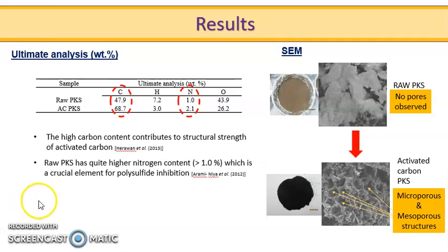Now let's look at the results. From the ultimate analysis, it proved that PKS is a suitable candidate for production of activated carbon cathode composite, since it has high carbon content, which contributes to the structural strength of the sulfur cathode, and it has high nitrogen content, which is above 1%. The high nitrogen content is a crucial element for polysulfide inhibition.